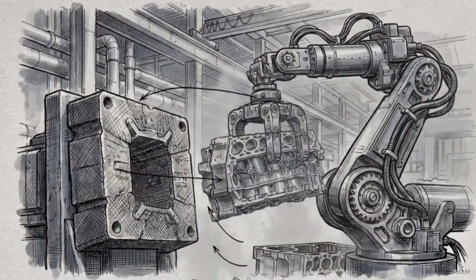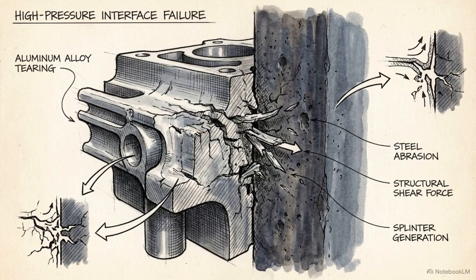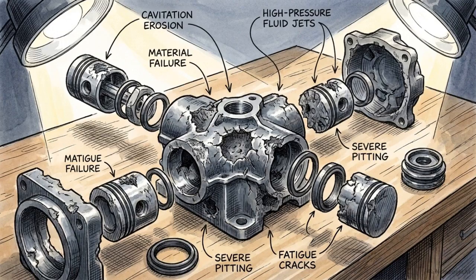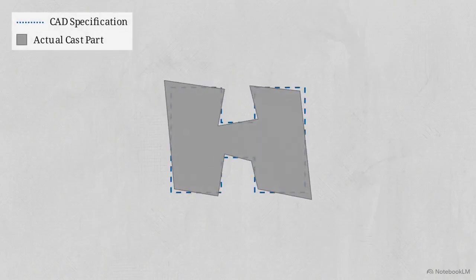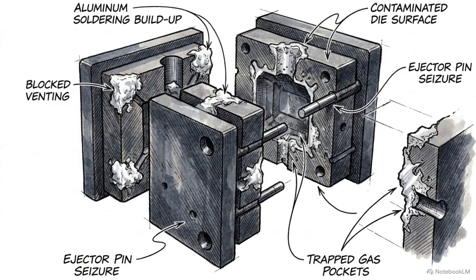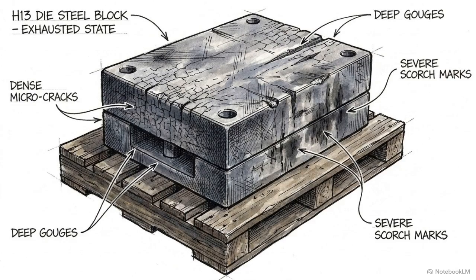All of these variables culminate in the final stage of the casting cycle, the forceful ejection of the part from the die. Because the metals have welded together, the sheer force of ejection leaves immediate physical damage. The casting will emerge with rough patches and an uneven surface finish where the bond finally sheared off. This creates a critical issue of dimensional inaccuracy. Layers of retained metal build up on the die, altering the precise geometry required to meet strict aerospace or automotive tolerances. On the tooling side, this constant stripping and welding inflicts cumulative damage on the H13 die steel, drastically reducing the operational lifespan of the mold.